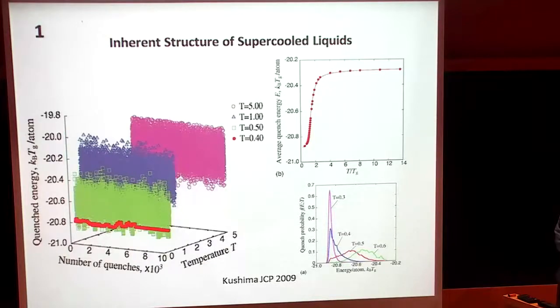I don't think there's any problem. I can show you. We should talk offline about this. At low enough densities, you do see the mesoscale structure becomes different. But for high densities, which is typically where this kind of formulation is used, you do find the structure of the inherent structures to be significantly different from what we start with, but there is no medium or longer range change.